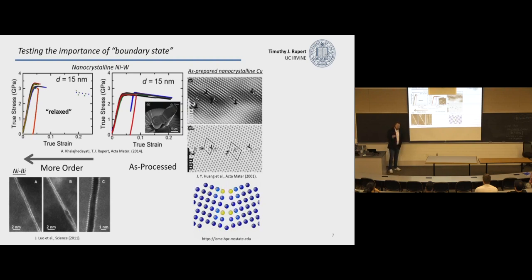There's other ways you can think about this. So when we're relaxing those samples, we're making the grain boundary structure more ordered. You can also do this with chemistry. So in this example of nickel bismuth, if you dope with bismuth, it goes to the grain boundaries. It forms a very ordered segregation pattern. These bonds are stretched and they're just ready to break. Okay? So what we learned here is that more ordered is bad.